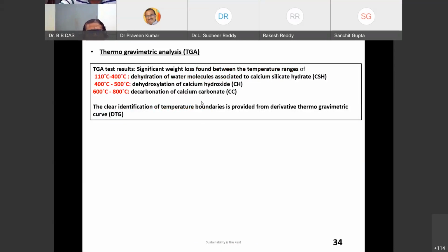All right. Now let us move to the thermogravimetric analysis, that is, moving to the advanced hydration studies. If you go to the literature of thermogravimetric analysis, most people talk about three different phases in a cementitious system. 110 to 400 degrees is dehydration of water molecules associated with calcium silicate hydrate. 400 to 500, dehydroxylation of calcium hydroxide. 600 to 800 degrees, decarbonation of calcium carbonate. This is what you have to understand is happening when you do thermogravimetric analysis.